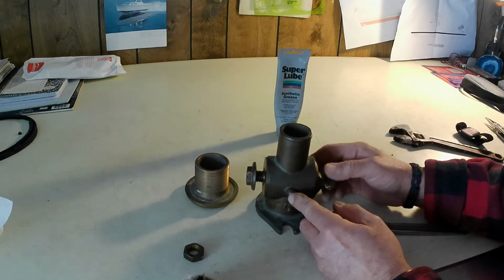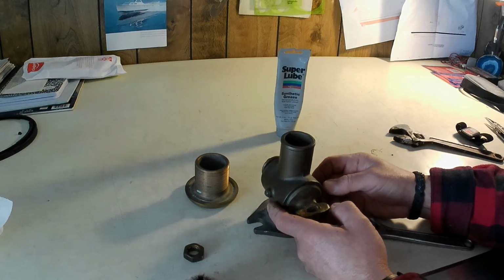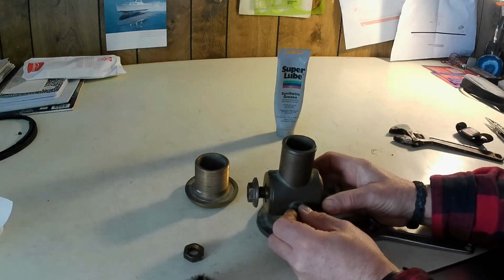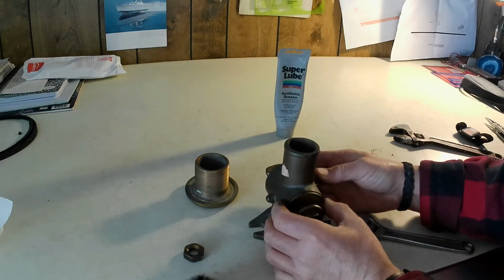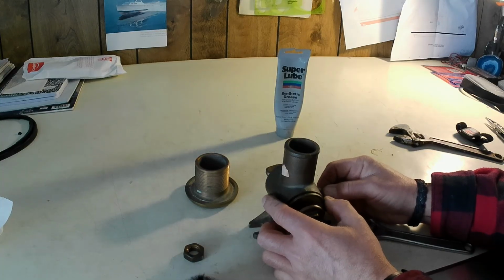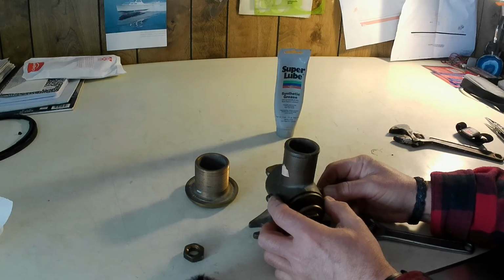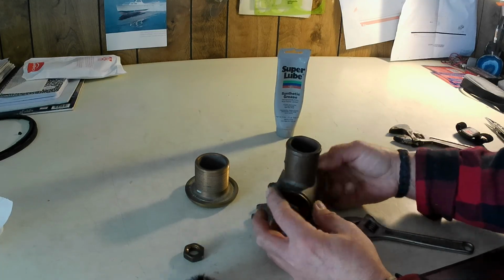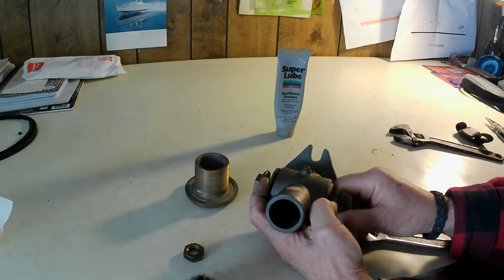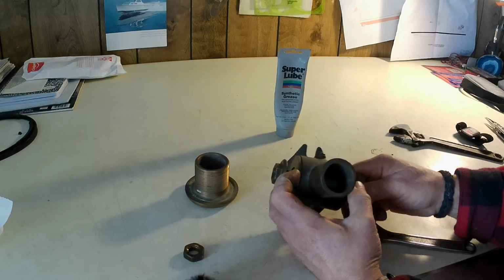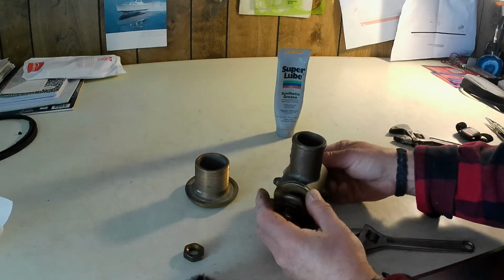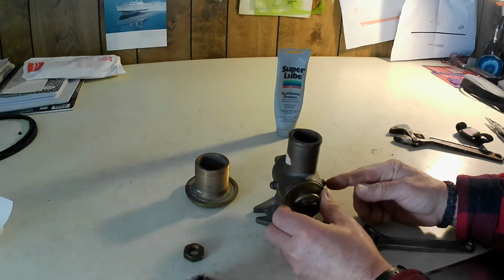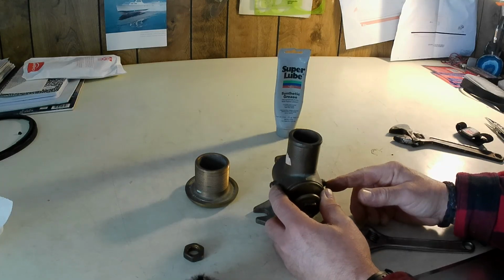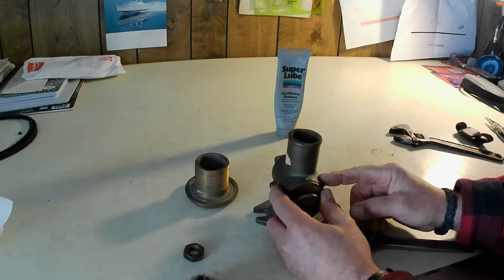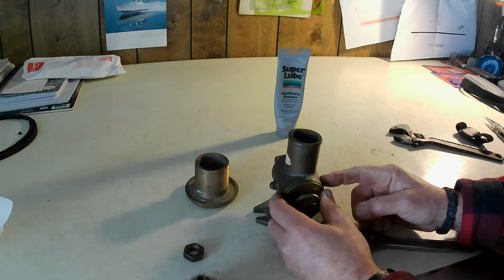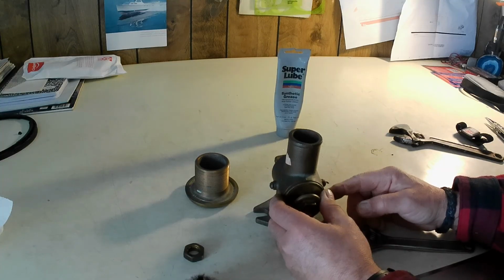So you might say, well, you've got these two fittings on the sides. Why don't you just put a grease Zerk fitting on those? You can do that, but what you have to understand in doing that is that these are not designed to be grease fitting points. These are drains. Again, think about this valve in the closed position. You've now winterized your boat. Shut this down so that you can't have a frozen hose sink the boat. The purpose of these two plugs is that you then remove them and drain the water out of the body of this valve, because if this remains full of seawater and it freezes, even 37,000 psi bronze will crack.